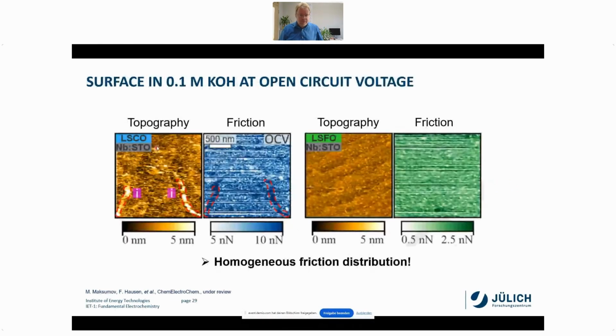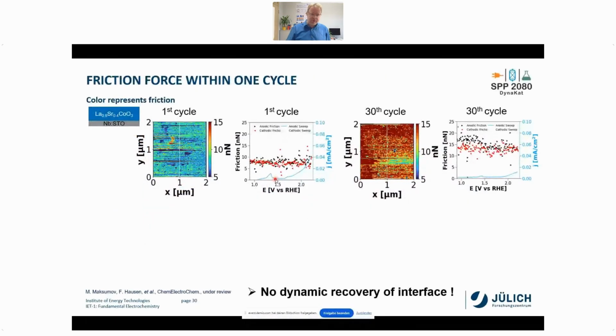So to start with that, we looked at the topography of these two materials, and you see before they are run, you see here a stepwise structure. They are really nice. They have some defects from time to time, which then is also seen in the friction. That was also what Ini showed you with the step edges. But in principle, we have a really homogeneous friction distribution on our materials before we use them electrochemically. So that changes then when we use them electrochemically.